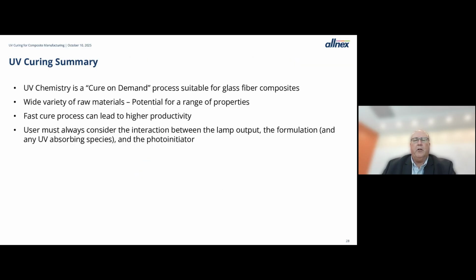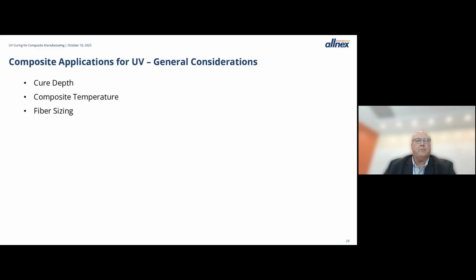So UV chemistry: cure on demand, a process very suitable for glass fiber composites, a wide range of raw materials, and a very fast process. But again, and I'm going to emphasize this over and over, you have to consider the interaction between the lamp output, the absorbance of the photoinitiator, and the formulation in order to get a good cure. So what are some things to consider when you want to use UV in a composite formulation? Here are three general considerations: cure depth, composite temperature, and fiber sizing.